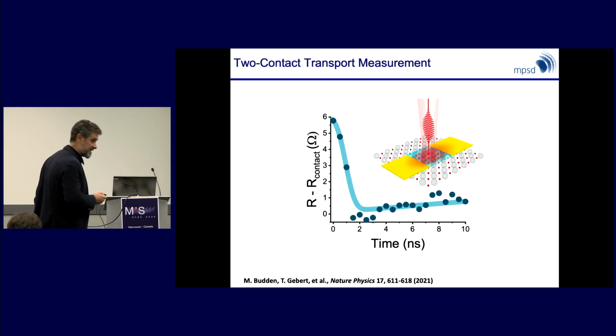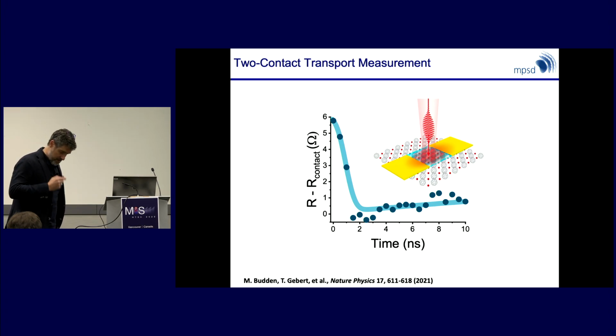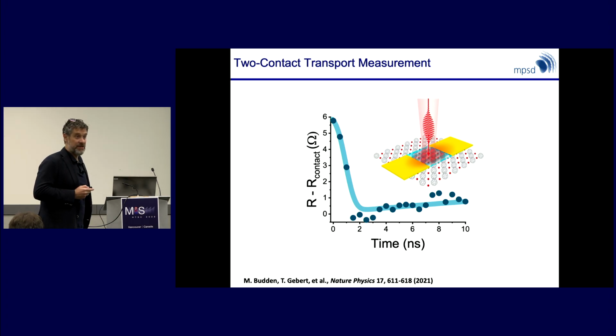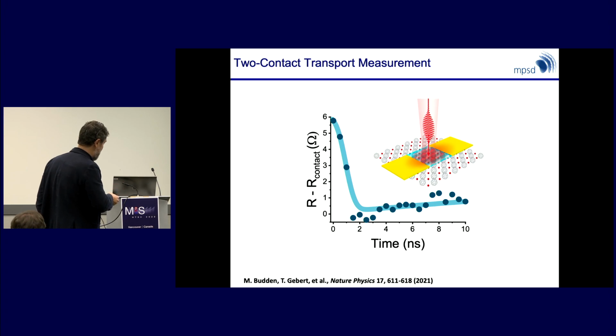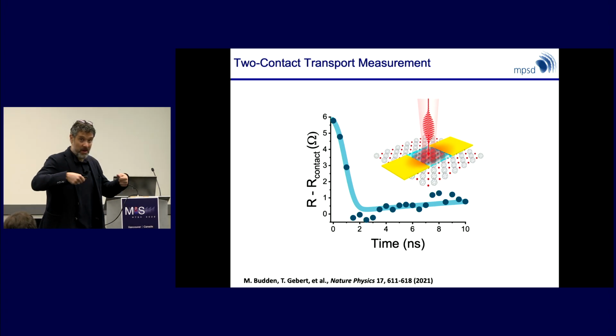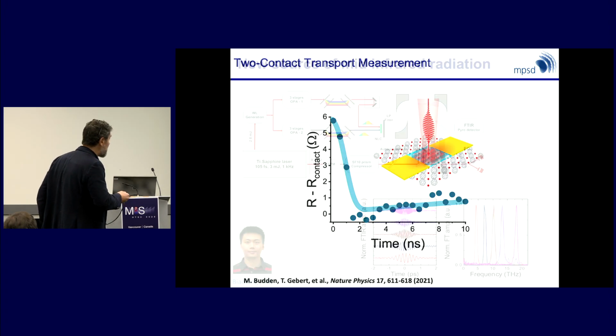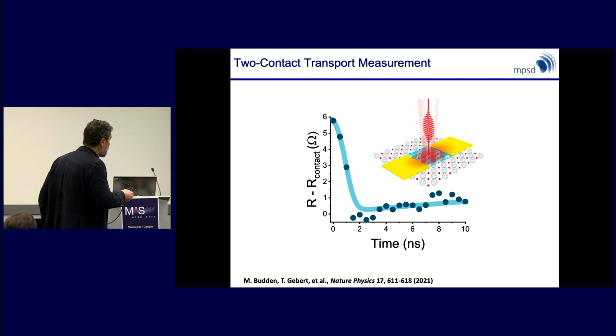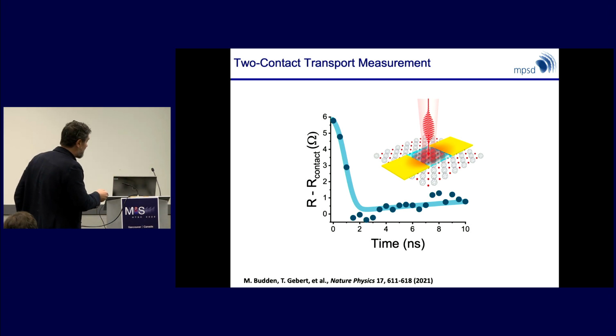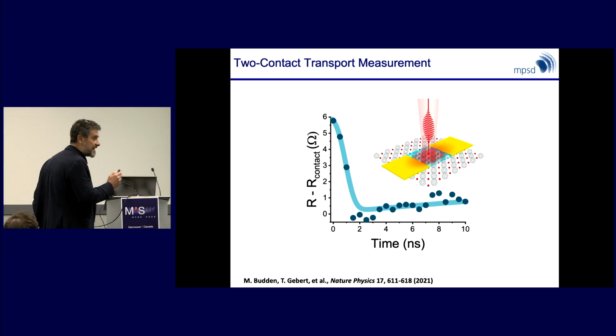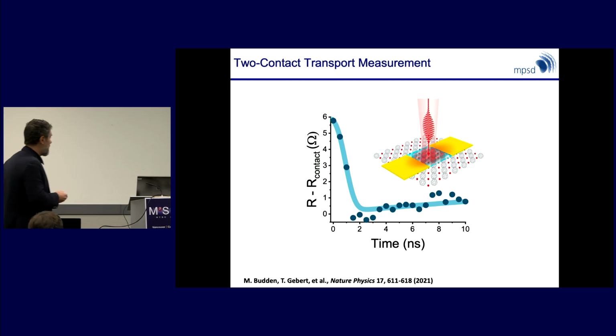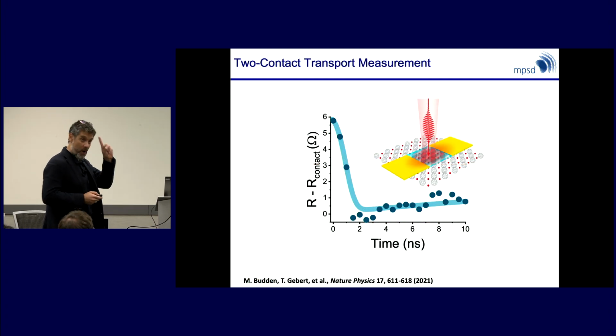What gave us some degree of confidence that these fits might be appropriately reproducing the true zero frequency resistance is that Matthias measured the 2-probe resistivity, with the caveat that we had to subtract away the contact resistance, and we assumed that the contact resistance would not be a function of time in the photoexcited state. Within a number of caveats, we've been as careful as we could, and we found a resistance which is in the ballpark of 0, plus or minus some error bar, which is at least consistent with the extrapolated rho 0 from the optical measurements. So this was one of the three things that I want to tell you.